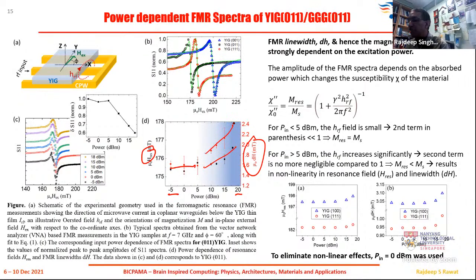They start to change over there. So we did not want to work in this particular region. We wanted to work somewhere over here. And the reason is very simple: when you apply higher RF power, you are going to apply a higher field, and that is going to make your magnetization vector precess into a larger cone radius.